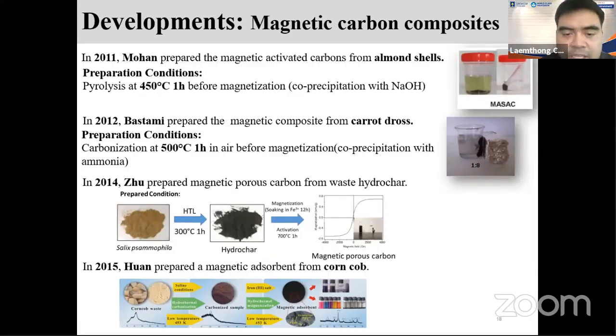Let's talk about, in this presentation, magnetization. They use a kind of iron to make the magnetization, which means they put the magnetic particles into the adsorbent matrix. This is the picture that they show in their work, where they can use just an external magnet. They already have the carbon adsorbent, which has magnetic particles entrapped inside the carbon matrix. So when they put a magnet next to it, it can attract this kind of fine particle, right?